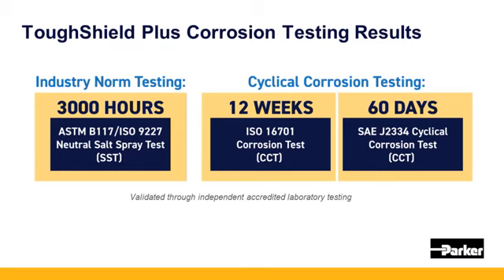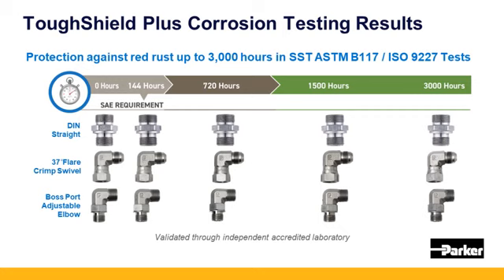But we're taking that a little bit further, and as you probably gathered through Yindong's discussion regarding cyclical corrosion testing, we're now going to be implementing cyclical corrosion testing in how we qualify our product. We use two fairly demanding cyclical corrosion tests, one being the ISO 16701 cyclical corrosion test, as well as the one that's more common here in North America, which is the SAE J2334. And again, the reason why these are becoming more common methods of evaluating and qualifying plating systems for corrosion resistance: some OEMs are already using cyclical corrosion tests, either these or derivatives of these. And again, it doesn't just rely on that static fog. It relies on the alternating cycles of humidity, dry heat, and changes in temperature to provide a bit more realistic approach of what you would see in the industry.